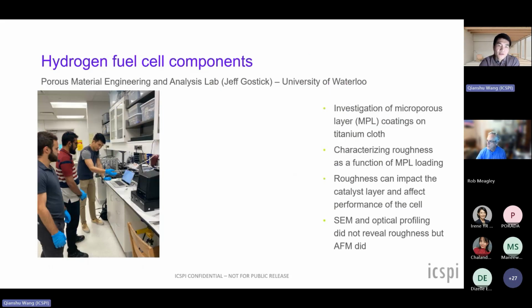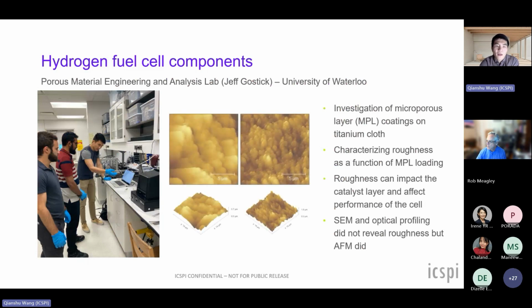Another example here, this is at the University of Waterloo. I actually paid a visit to the lab of Professor Jeff Gostick, and I helped him investigate microporous layer coatings on titanium cloth. Characterizing roughness is important as a function of MPL loading. We just visited in the morning, and previously they were using SEM and optical profiling, but they weren't really revealing the roughnesses that they needed, but AFM did. The roughness can impact the catalyst layer and affect performance of the cell. We're able to take these scans using an instrument that we brought over. This was all done in a couple hours in the morning, and I ended up teaching his grad students how to use the tool by the end of that trip as well.